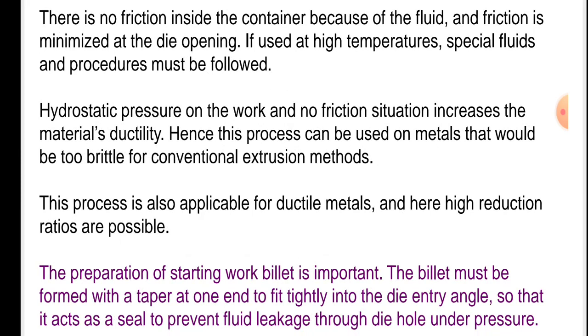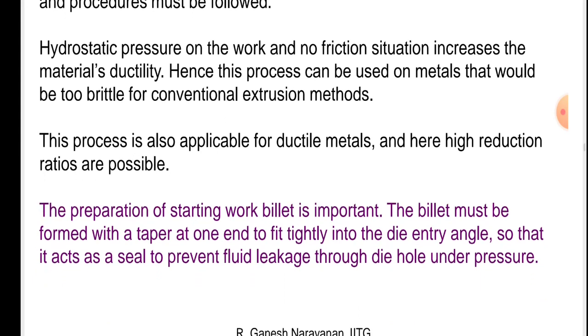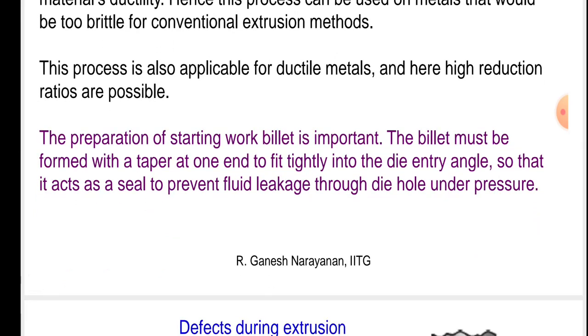Hydrostatic pressure on the work and no friction situation increases the material's ductility. Hence this process can be used on metals that would be too brittle for conventional extrusion methods. This process is also applicable for ductile metals, and here high reduction ratios are possible.